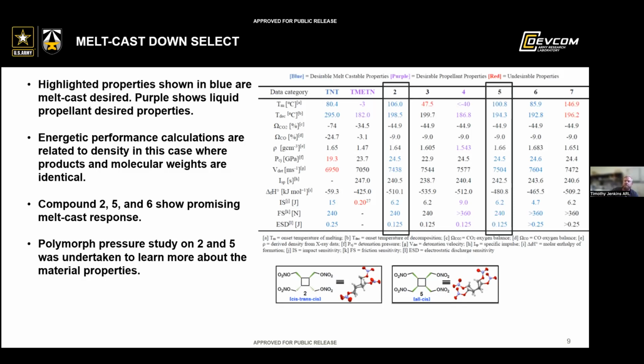And you can see I've highlighted two of them, compound 2, which is the cis-trans-cis structure, and compound 5, which is the all-cis structure. So these are very, very similar to each other. In fact, you can look down, and the only small difference that you see is a slight difference in the density between the two, due to the way that they pack in the crystal. This then contributes to the slight difference in detonation velocity that you see. Compound 6 also has a lot of interest as a potential melt cast energetic, but this is a regioisomer to these materials, and we wanted to look at the differences we could determine from a stereoisomer standpoint.